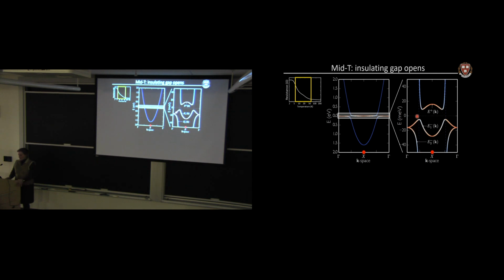then the conduction band starts to see the F states, starts to congregate and try to screen those F states. So when the d band starts interacting with the F states, they hybridize and open a gap in the density of states around the Fermi level. And that gap is what makes it an insulator. And so the interesting thing here is that you see that now the F state has popped above the d state. So that starts to look like a topological insulator. It's that band inversion that we need for the interior to have this topological twist in the band structure.